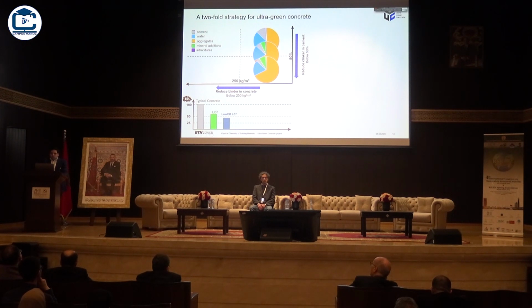I already showed you that in some markets and in some applications, it actually makes a lot of sense to think that we can go lower and we can reduce the clinker content even further. But we cannot go to zero. There is a higher price to pay in terms of efficiency of performance as low as we go in the clinker content. So there is definitely a reduction in the amount of CO2 and clinker that is plateauing up to a certain point. So we cannot go infinitely down in the clinker concrete avenue.